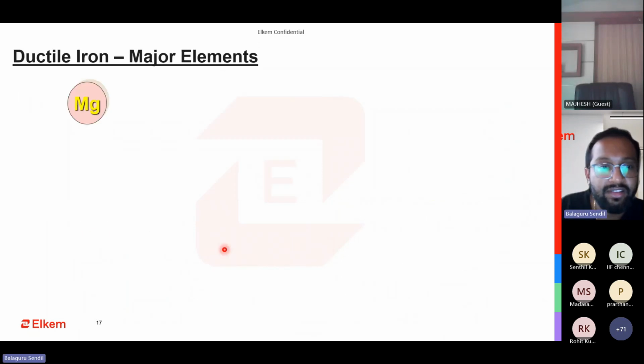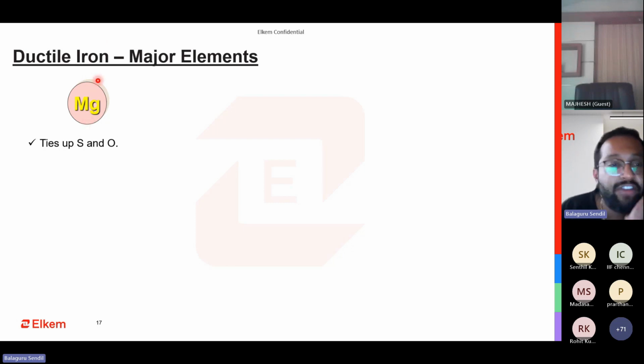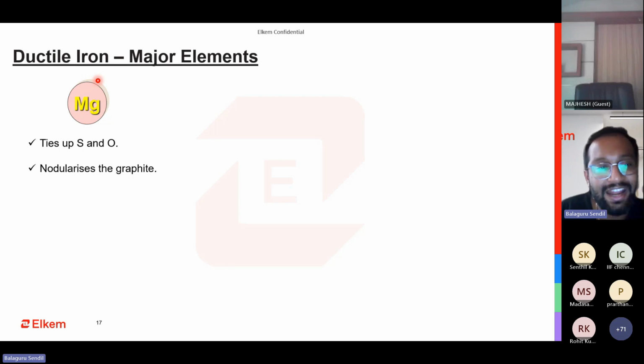In ductile iron, as I said, magnesium is the major element. What does it do? It ties up the sulfur and oxygen. It creates the nucleating site with MgS in the core and then an oxide shell, which makes sure that you have nice graphite growth happening on that nucleating site created with the help of magnesium. And it nodularizes the graphite. Basically, it adjusts the growth speed, and it makes the graphite round and very spherical in shape. Unfortunately, it increases the chill tendency.